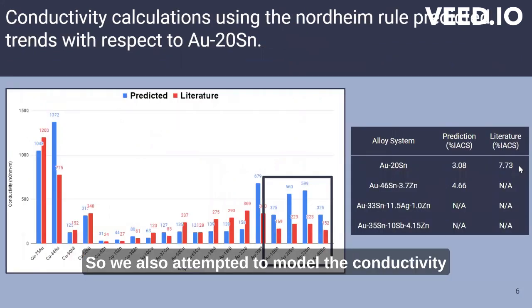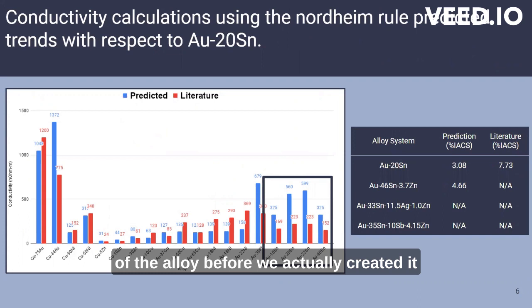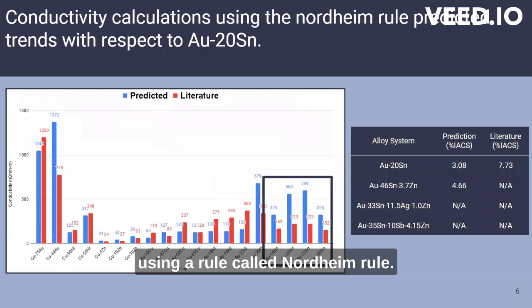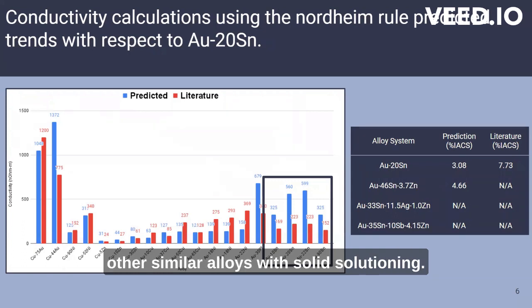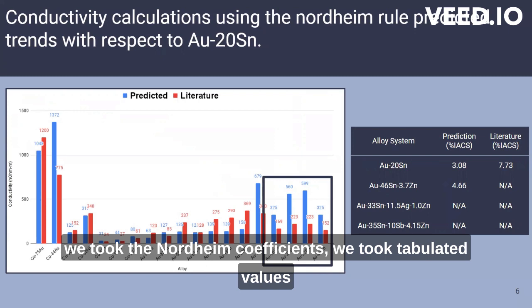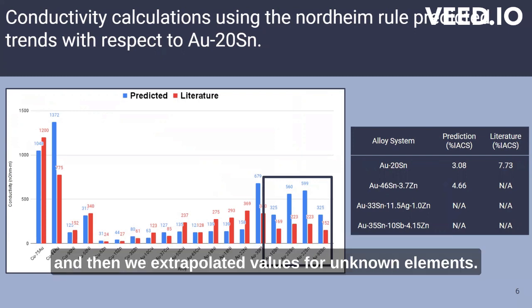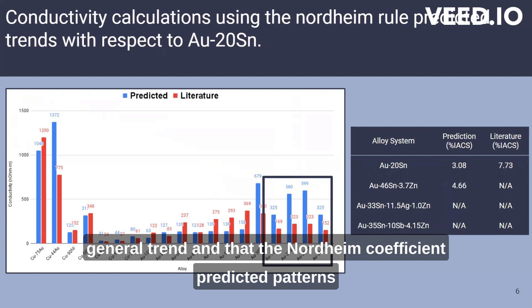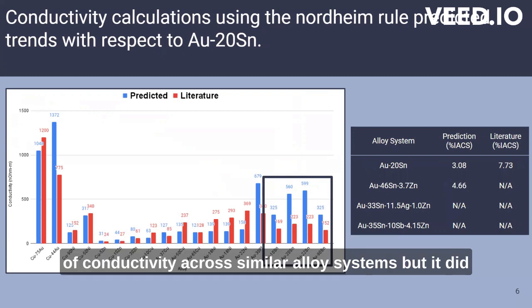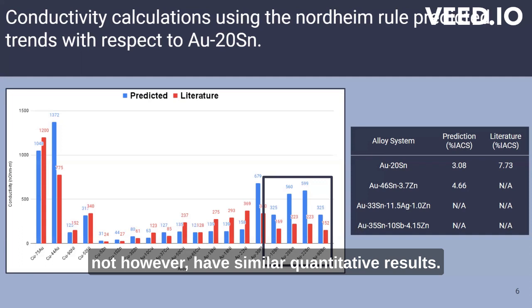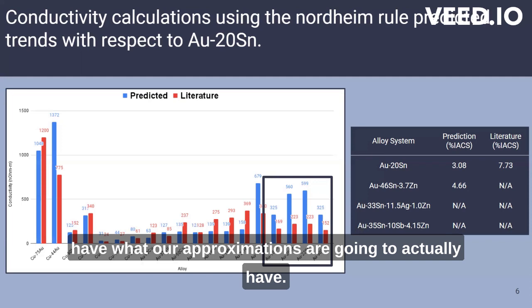So we also attempted to model the conductivity of the alloy before we actually created it using a rule called the Nordheim rule. This is an approximation used for other similar alloys with solid solutioning. Now, when we did this, we took the Nordheim coefficients, we took tabulated values, and then we extrapolated values for unknown elements. And what we found is that there was a general trend, and that the Nordheim coefficient predicted patterns of conductivity across similar alloy systems, but it did not, however, have similar quantitative results. So we could use this as a reference point for comparing alloy to alloy, but we can't expect it to match what our approximations are actually going to have.